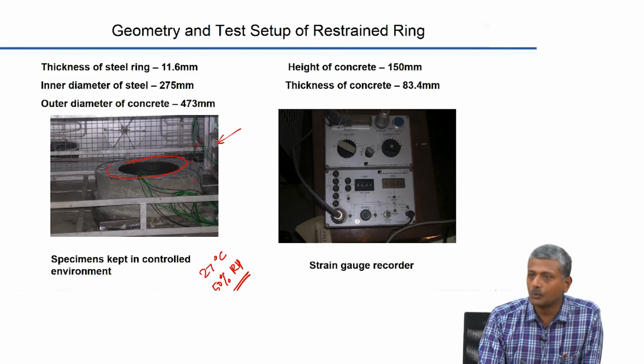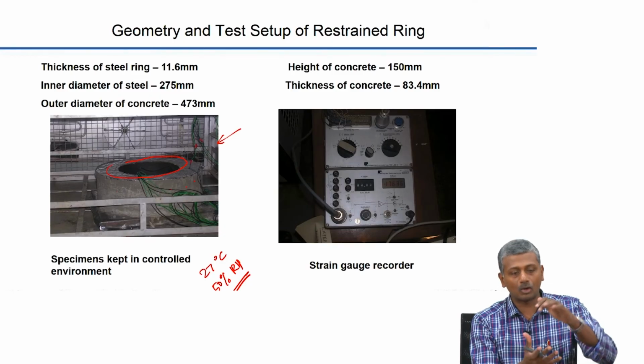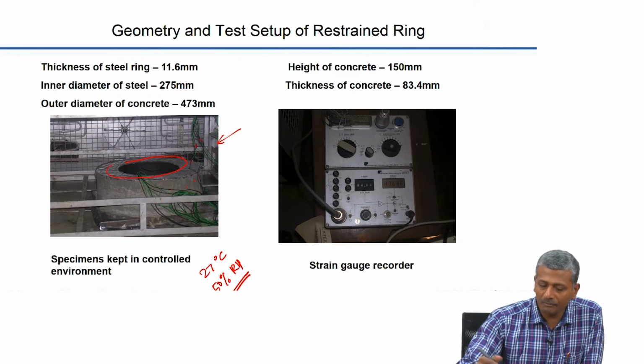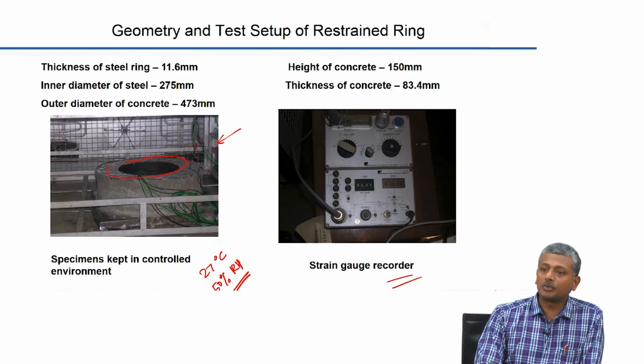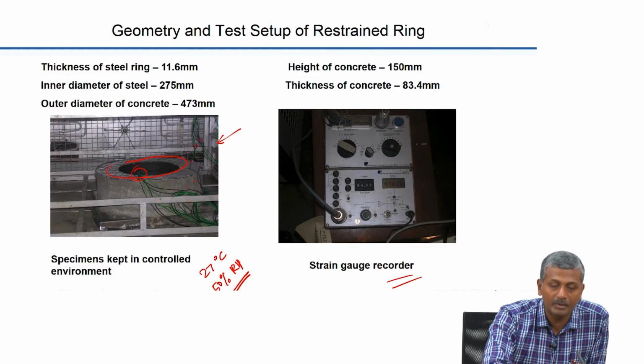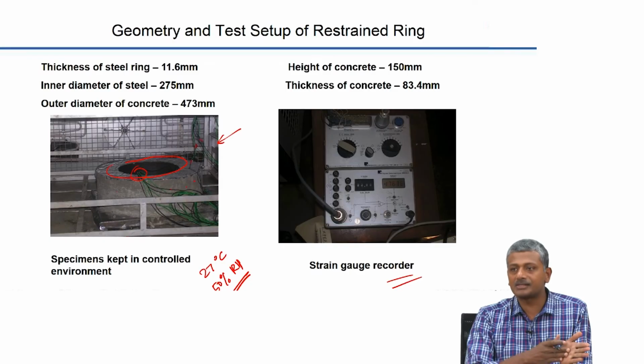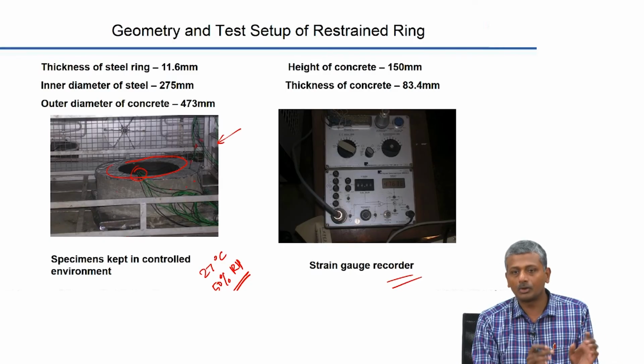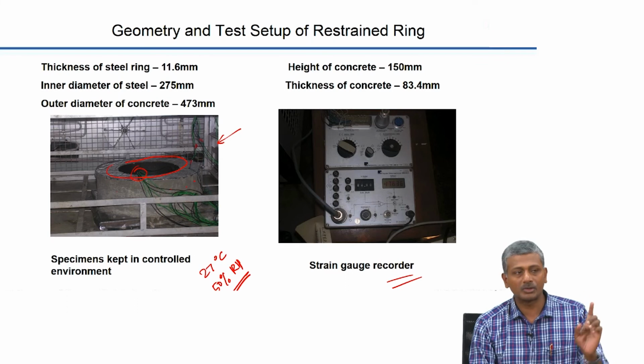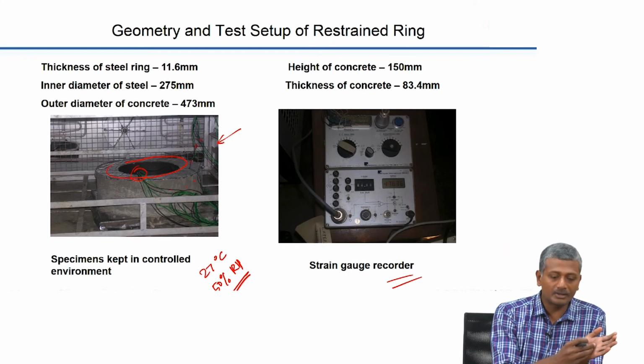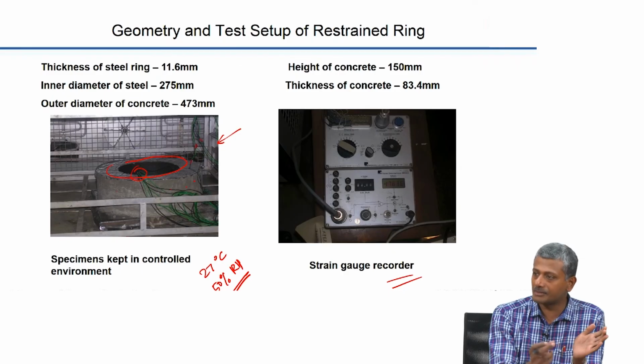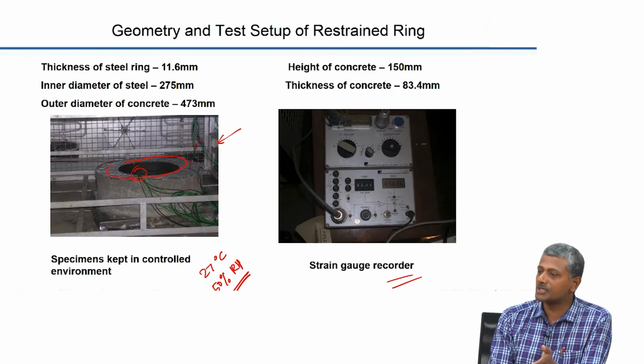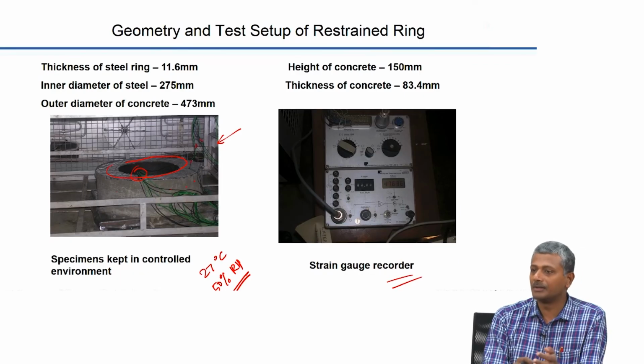The equation that I showed you was essentially for circumferential drying and not drying from the top and bottom. We had a strain gauge recorder which had to be manually operated to collect the strain data from time to time. You can see the wires that are coming out of the strain gauges. These were pasted on the inside surface of the steel in the hoop direction, not longitudinal, and I think there were 3 strain gauges pasted on every steel ring. In those days we did not have a data acquisition system which could automatically acquire the strain data, so we had to manually collect it from time to time.